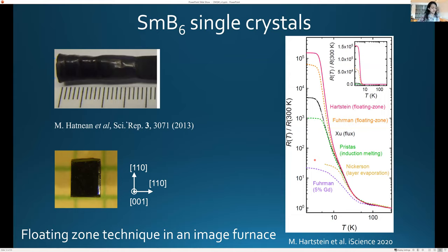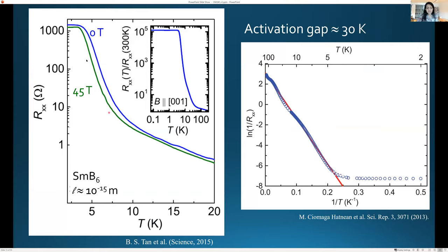Okay. So when we put this in a magnetic field, you can see the magnetic field has very little effect. So the blue line here is a resistivity at 0 tesla. When we apply 45 tesla, and this is also quite unique to samarium hexaboride, that very high fields, even up to 100 tesla, actually don't metallize the system. They barely change the gap by maybe 10 or 20% by 100 tesla, implying that the g factor is probably very small because the Zeeman effect seems to be doing very little to this material. So at 45 tesla, we're confident it's still a good insulator.